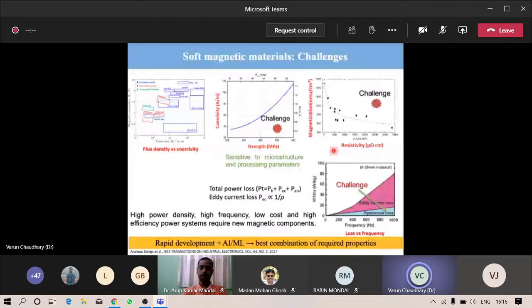The same is the case with resistivity. If we increase the resistivity, the saturation magnetization decreases. So why do we need high resistivity? Resistivity is inversely proportional to the eddy current loss. So we want to decrease the eddy current loss and therefore the total power loss in electric machines. So this is a very messy engineering problem and can be solved by using AI and ML kinds of approaches. However, the difficulty is that we don't have enough database. For using this kind of approach, we need a huge database, then only we can utilize AI and ML. So rapid development along with AI and ML can give us the best combination of required properties to use these kinds of materials in advanced electric machines.